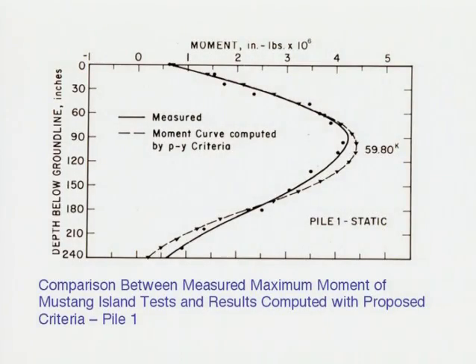So we have to make adjustments if we have a pile group to design, to take into account the influence of one pile on an adjacent one. Now, I'll not show the PY curves that were developed here at this site, but just move ahead to where we make a comparison between the use of the PY curves to compute bending moment and the bending moment that was measured for a load of almost 60 kips. And you can see that we're able to compute fairly accurately.